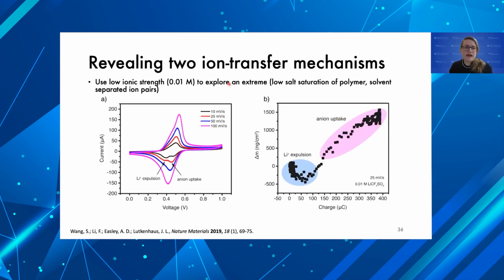To reveal the mechanism of the ion transfer, what we did was we went to a much lower ionic strength to tease out that lower potential peak. So when we go to this really low ionic strength, you're forcing the electrolyte to be in a highly solvated condition where each ion has a solvation shell that's very well developed.